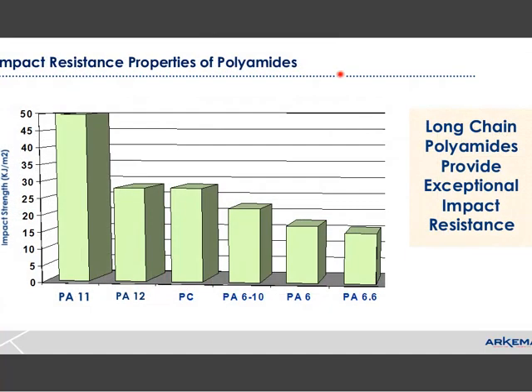One of the most important benefits of PA11 specifically is its higher impact strength compared to all the other polyamides. Polyamide 12 is by itself very good impact, having performance similar to polycarbonate. But polyamide 11 is significantly higher than that, having impact strength greater than 50 kilojoules per meter squared.